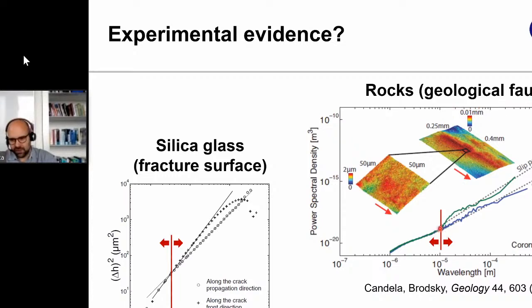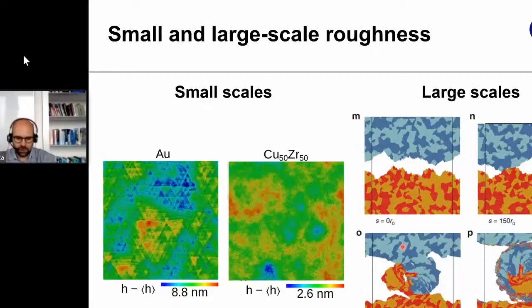A length scale below which, in this case, the surface becomes isotropic, above it, it's anisotropic, but there's also a change in scaling exponent for some of the directions. So there seems to be a change in mechanism at something on the order of the process zone size. So what I've talked mainly about today would be the mechanism for the evolution of small-scale roughness. Jean-François and Ramin have done beautiful work on what happens at larger scales. So this is what has happened recently in the simulation community.